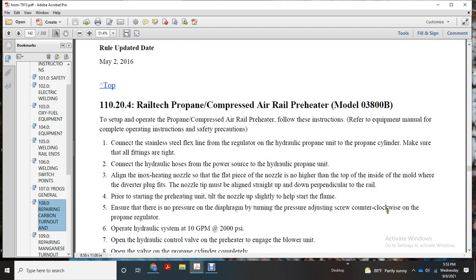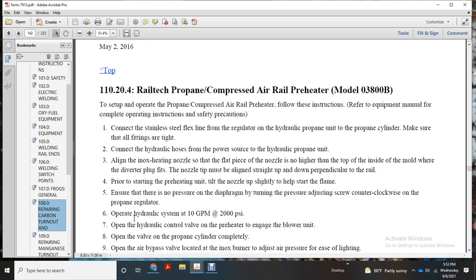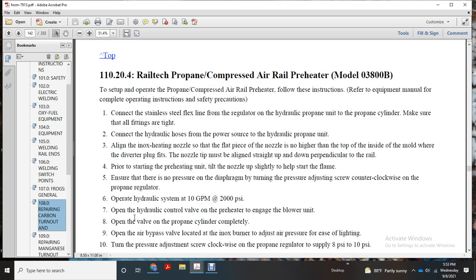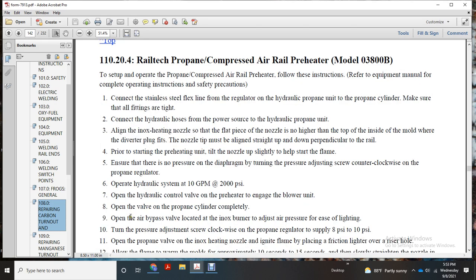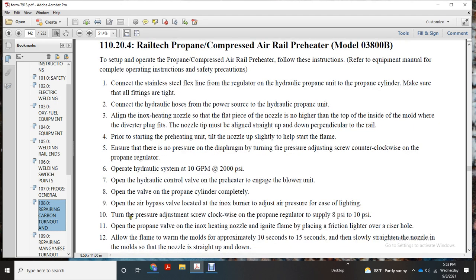Turn the pressure adjusting screw counterclockwise on the propane regulator. Open the hydraulic system to 10 gallons per minute at 2000 psi. Open the hydraulic control valve of the preheater and start the blower unit. Open the valve of the propane cylinder completely. Open the air bypass valve located on the inox burner and adjust the air pressure for ease of lighting. Turn the pressure adjusting screw clockwise on the propane regulator to supply 8 to 10 psi. Open the propane valve on the inox heating nozzle.